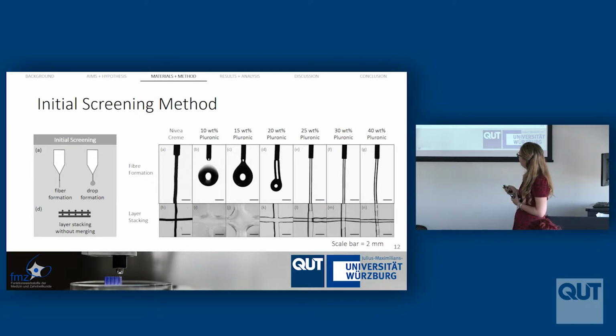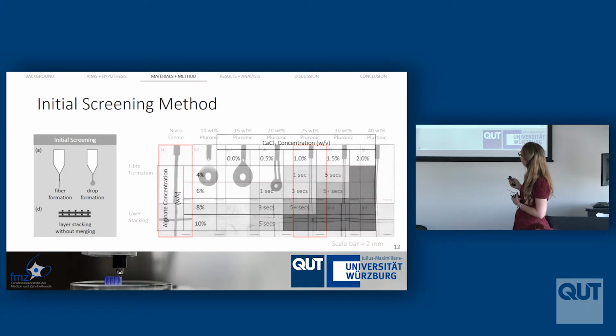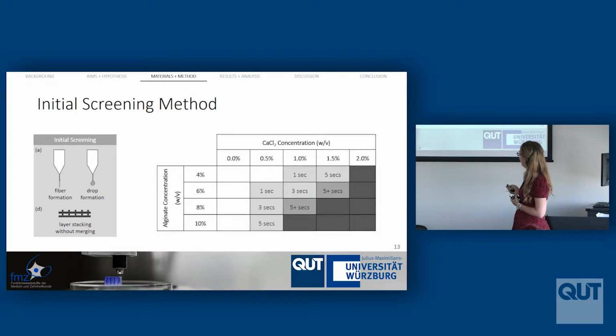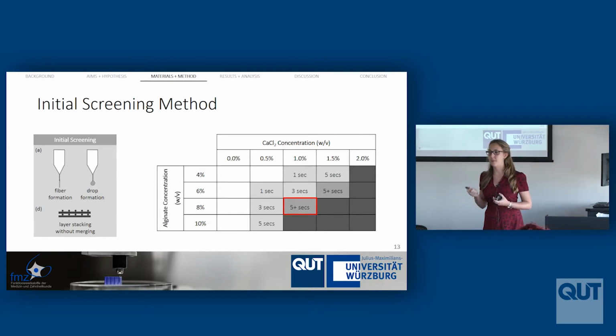And then I'm also showing you results for different concentrations of alginate and then different cross-linking solutions as well. And so we found out that using 8% alginate with 1% of our calcium chloride solution gave us a really nice hydrogel that was able to satisfy those two conditions.